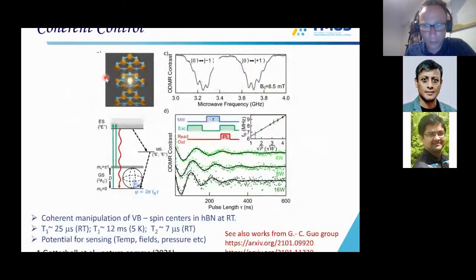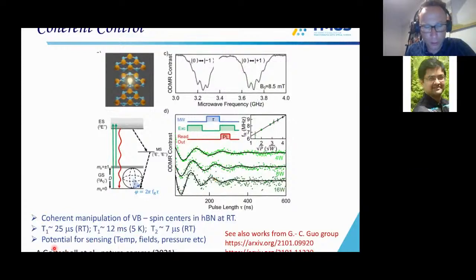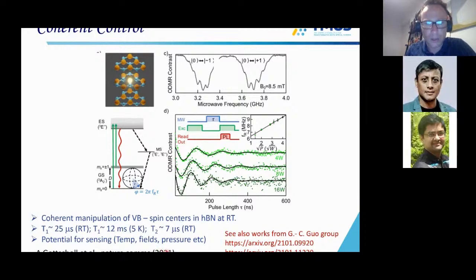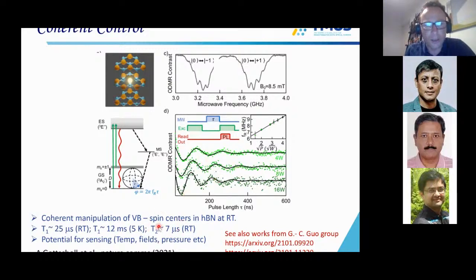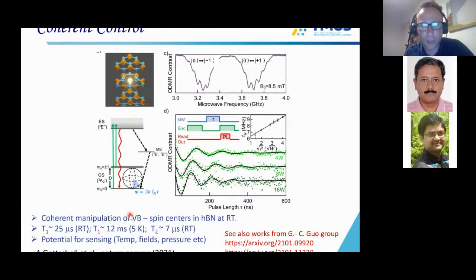A lot of this work was done by Andreas Gottscholl in the group of Professor Vladimir Dyakonov in Würzburg. And so they also measured the coherence time. It's not ideal, of course, but somewhere around several microseconds. It's pretty much limited by the boron and nitrogen spins in your lattice.